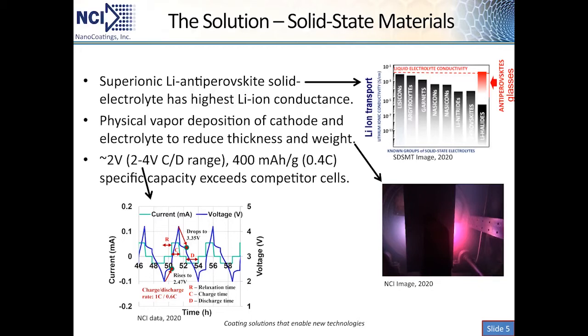The School of Mines has performed charge-discharge testing on coin cells. These are CR 2025 geometry, and you can see in the lower left figure that our voltage range for each cell has been 2 to 4 volts charge-discharge, a specific capacity of up to 400 mAh per gram, although this is at a 0.4 C charging rate. For discharge rate, we're at about 115 mAh per gram at 1.2 C, so we're slightly lower than the Navy requirement, but we feel confident that we can get there. And these specific capacities do exceed competitor cells.